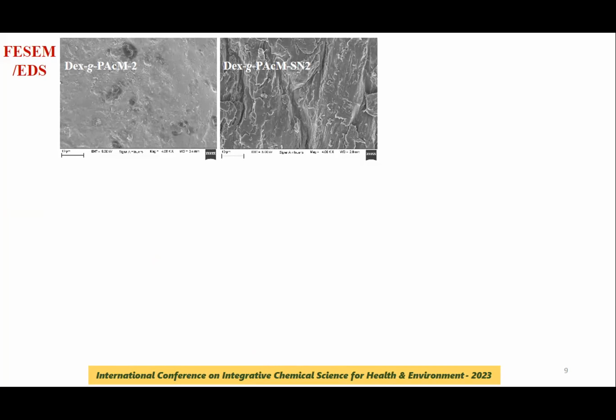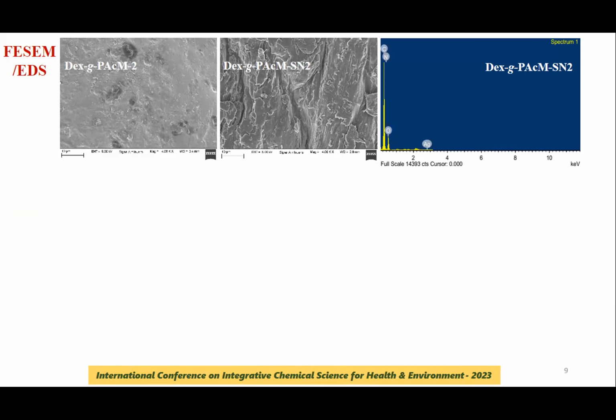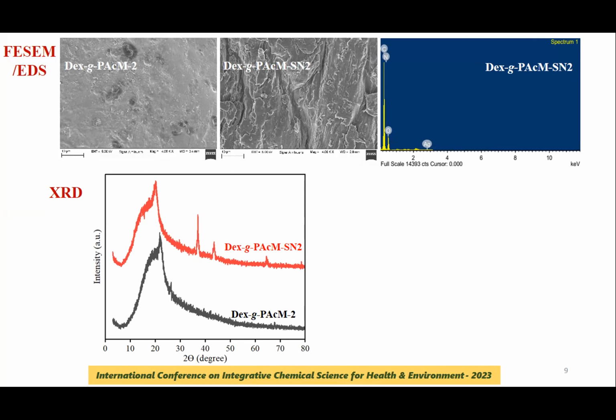Then characterization by FESEM and EDS: the hydrogel shows a smooth surface with few distributed pores, but upon incorporation of nanoparticles, the surface of the material becomes more undulated and the pores are interconnected. EDS confirms the elemental distribution present in the system, particularly in this dextran nanocomposite hydrogel. XRD shows an amorphous nature for the hydrogel, but upon incorporation of silver nanoparticles, the appearance of crystalline peaks reveals the incorporation of silver nanoparticles. HRTEM further confirms the presence of silver nanoparticles in the polymer matrix.